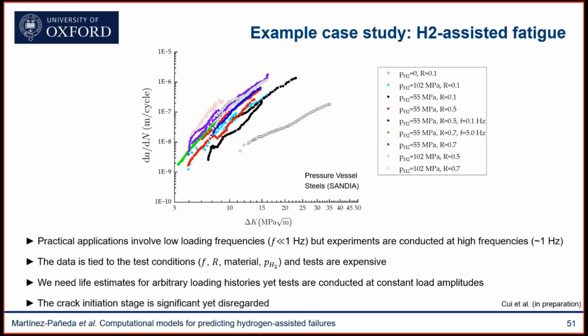One is that there's a sensitivity to the loading frequency. Normally in fatigue, as you know, we don't care about the loading frequency, but the moment we have hydrogen, we have diffusion, and therefore timescales matter, and there's a sensitivity to the loading frequency. And we know that the lower the loading frequency, the higher the susceptibility to hydrogen embrittlement. So we want to actually test at very, very low loading frequencies.